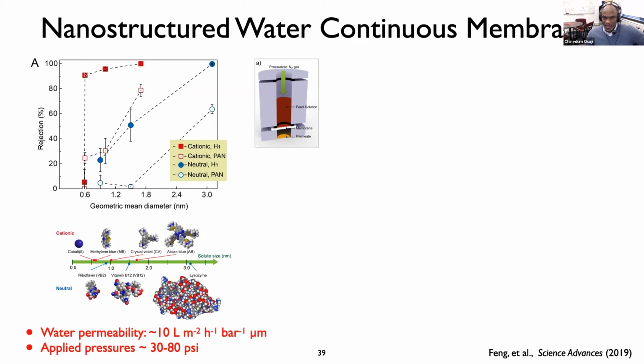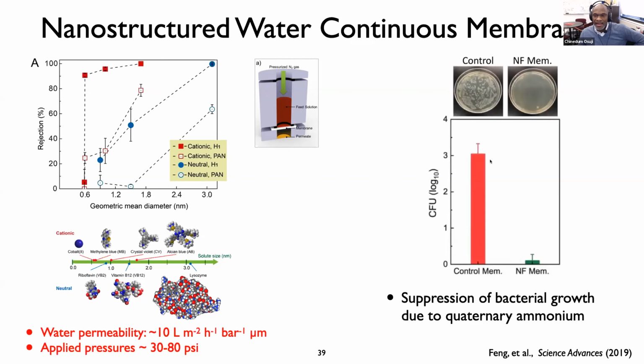And of course, that cutoff behavior was a lot stronger for cationic solutes than it was for neutral solutes, because the surface of those cylindrical objects is positively charged due to the presence of that quaternary ammonium species. We had water permeabilities on the order of 10 LMH per bar, and this is thickness normalized. And we were working at fairly low applied pressures of about 30 to 80 PSI, right? Reverse osmosis is typically at something like 800 PSI, so a decent order of magnitude higher pressure. And these were interesting membranes as well because they were able to suppress bacterial growth due to the presence of that quaternary ammonium species. And so that has positive implications for fouling and control of fouling.